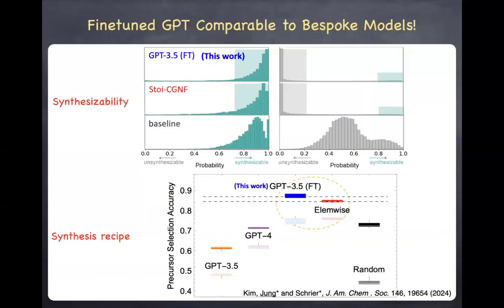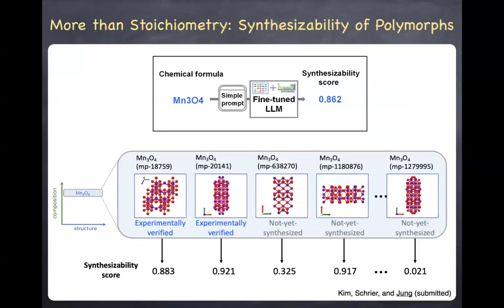Now, these synthesizability and synthesis recipes are both based on stoichiometry for the compounds. But at the end of the day, when you synthesize a particular compound, you really mean not the composition, but the structure, right? For example, if Mn3O4 is predicted to be synthesizable with a high score of 0.862, close to 1, what structure do we really mean? Because there could be multiple different polymorphs with the same stoichiometry.